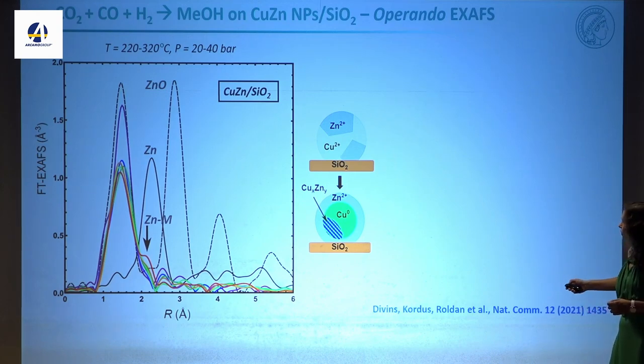So we learned from this data with the X-ray photoelectron spectroscopy that we have the zinc oxide shell, but then under reaction conditions, over time, you see the formation of a brass phase also. So you have a mix. It's not all brass, it's not all metallic. There is a mix of brass, metallic copper, and this zinc oxide shell.